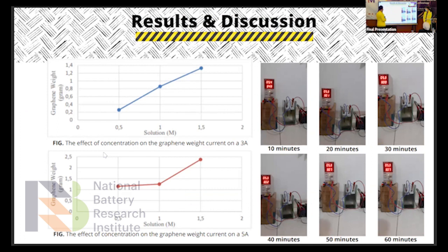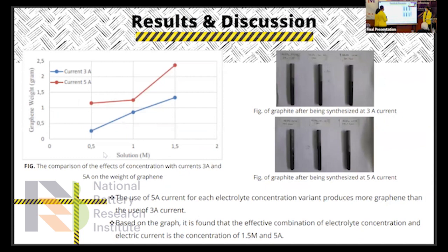From this graph, we can see the effect of concentration on the graphene weight at a current of 3 ampere. And in this graph, we can see the effect of concentration on the graphene weight at a current of 5 ampere. So this figure shows the process of synthesis. This picture is at 3 ampere with a concentration of 0.5 molar. This picture is taken at an interval of 10 minutes. And we do this process repeatedly for each sample. And here, we can see the comparison of the effect of the concentration with currents of 3 ampere and 5 ampere on the weight of graphene.